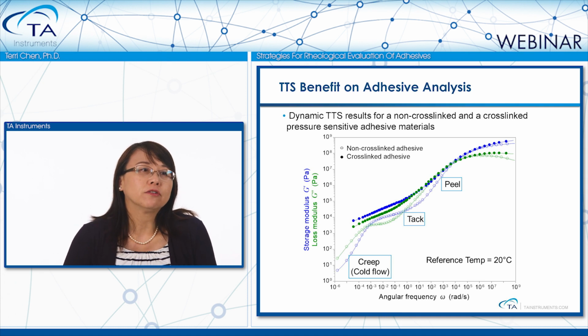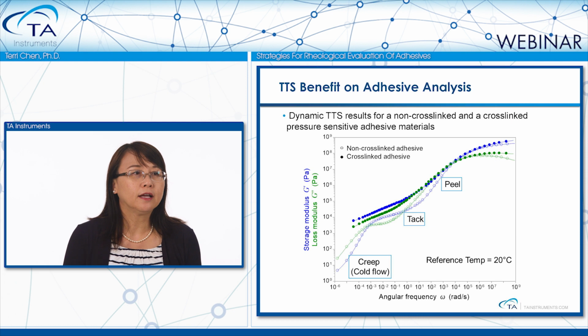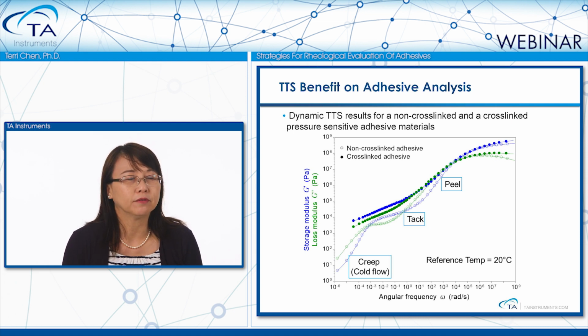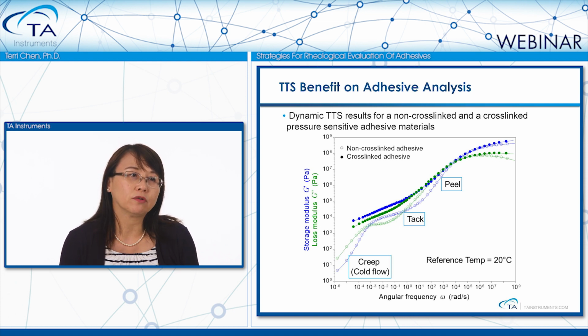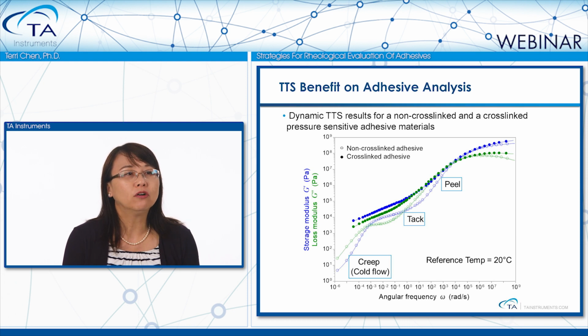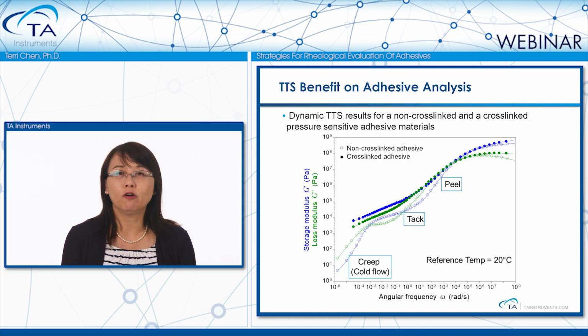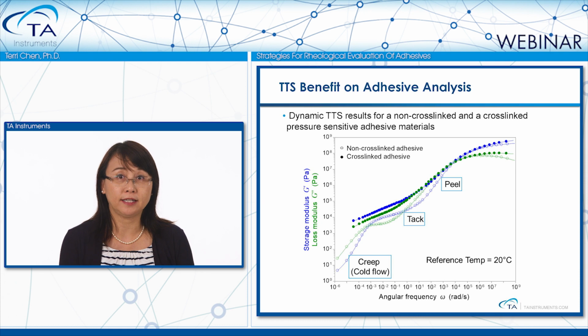This figure shows the overlay TTS master curves of a non-cross-linked and a cross-linked PSA sample. The reference temperature was selected at 20 degrees C. From these test results, we can quantitatively compare the tack, peel, and shear resistance performance of these two types of adhesives.